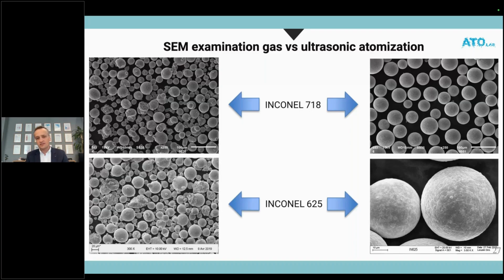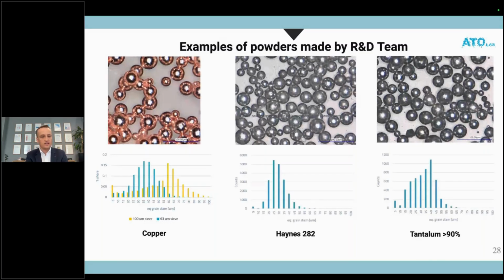In our case, we are not using any force. We are using only vibration, the ultrasonic vibration. We are putting it through the platform, and that's why we can eject a perfectly spherical metal powder from the molten metal. Here you can also check other examples like copper. We can easily atomize it with our induction melting system, and the efficiency is very nice for copper especially. The Haynes 282 material, or tantalum.